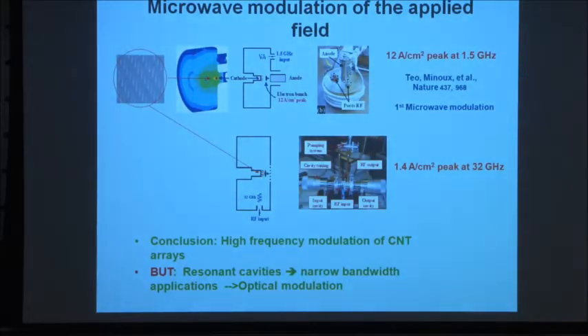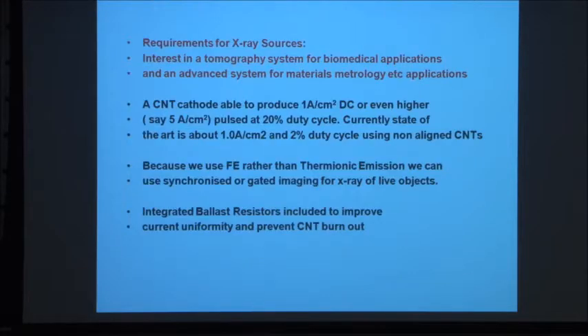We did this with Thales. We published it a while ago. We can get 12 amps per centimeter squared at 1.5 gigahertz and about 1.4 amps per centimeter squared at 32 gigahertz. Just using carbon nanotubes rather than thermionic emitters, they work very effectively. Very narrow bandwidth, we have to increase that, but there's work ongoing in Thales doing that. So there, the things we worked on a while ago.